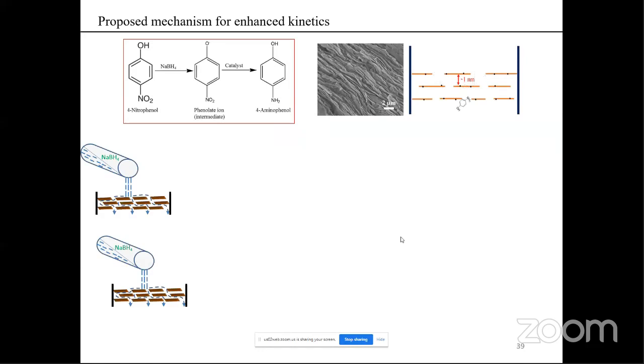Similarly, we can find out the exact mechanism, how it helps in doing the reactions. Basically, when you put sodium borohydride through this confinement between these layers, it gets inside the channel. That is why the reaction takes place much more easily, because the sodium borohydride cannot escape. It's a volatile compound. The hydride ions are volatile, so they will try to escape. So we need a much higher amount of sodium borohydride to do the reaction. But inside the confinement, this hydride ion cannot run away. So it has to undergo reaction with the nitrophenol to give us the aminophenol.